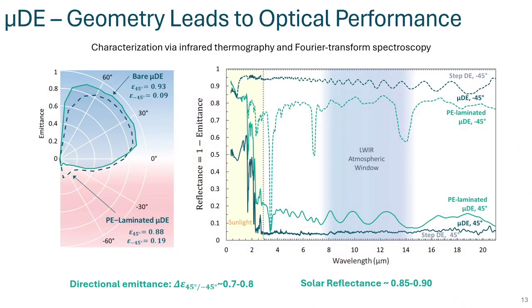We then quantitatively investigated the optical performance of this directional emitter. To do so, we used a range of characterization techniques from thermography to Fourier transform spectroscopy. On the left, we show the emittance of the directional emitter as a function of the angle from the horizon. As seen in the plot, above the horizon, the emitter exhibits high emittance, meaning it can effectively lose heat towards the sky. In contrast, below the horizon, the emittance drops significantly, indicating that the emitter effectively blocks terrestrial heat flows.